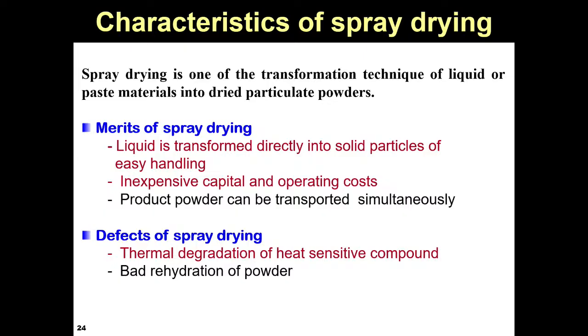Characteristics of spray drying: the merit of spray drying is that liquid is transformed directly into solid particles. As for the defects of spray drying, for drying we need high temperature gas, air. Therefore, there is thermal degradation of heat-sensitive compounds. So thermal degradation is important. And then we also have to think about the homogenization process. Also, you have to see that there is some kind of radical formation.